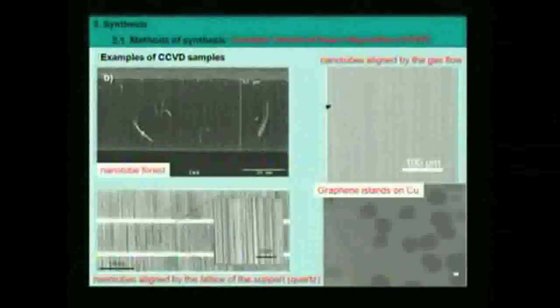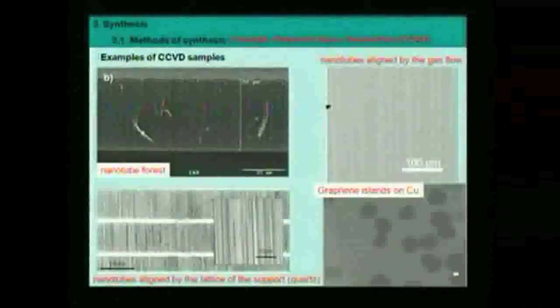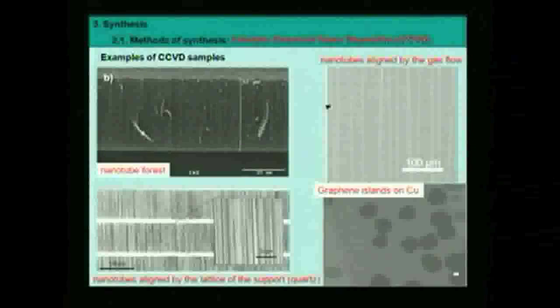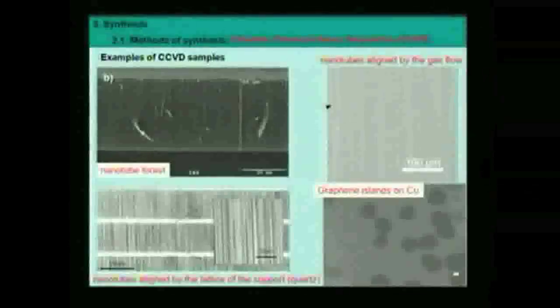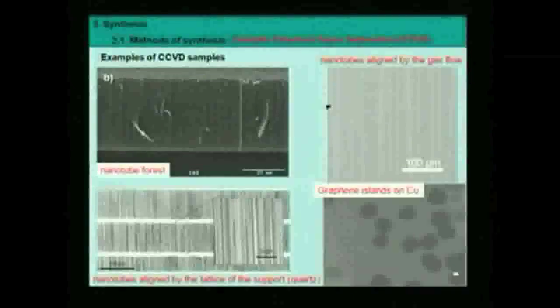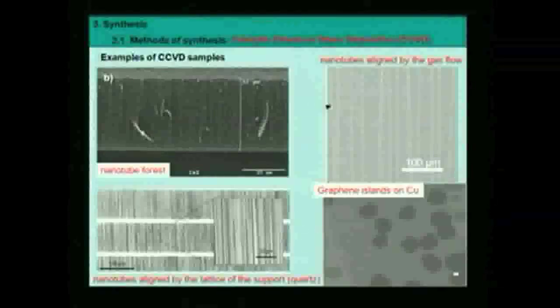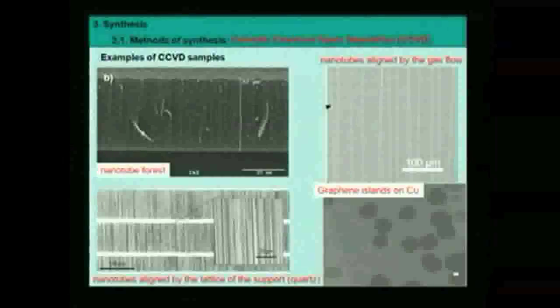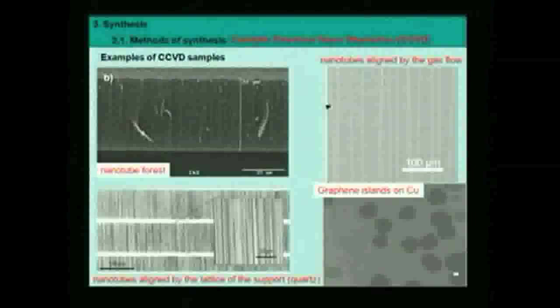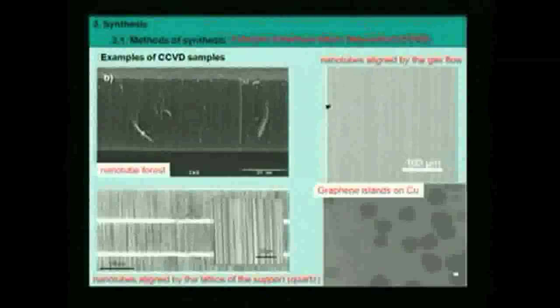Another way to orientate the nanotubes during the growth is to use a special support which is crystalline like quartz, and on some special faces of those substrates you can have an orientation of the nanotubes along a special lattice direction of the support. So this is a growth which is lattice oriented or lattice aligned. As you can see here, many nanotubes, very dense, all aligned along the same direction, along the same lattice direction of the support.